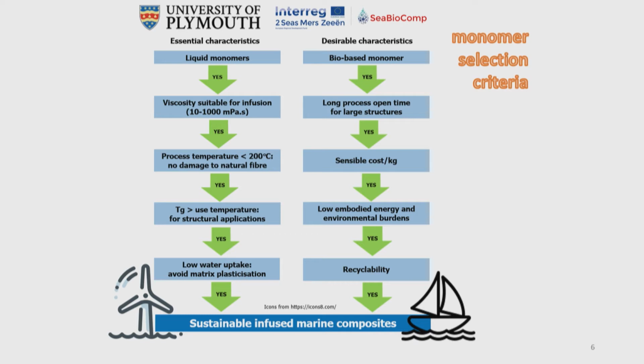And if we're going to put it in the marine environment, we want a low moisture uptake because moisture drops the glass transition temperature. There are also desirable characteristics in the context of the SeaBioComp project: that it be a bio-based monomer, that the process time is long enough to make large structures, that it's a sensible cost per kilogram, that there is low embodied energy and low environmental burdens, and it's recyclable. So we set ourselves quite a demanding series of constraints in order to make sustainable infused marine composites.